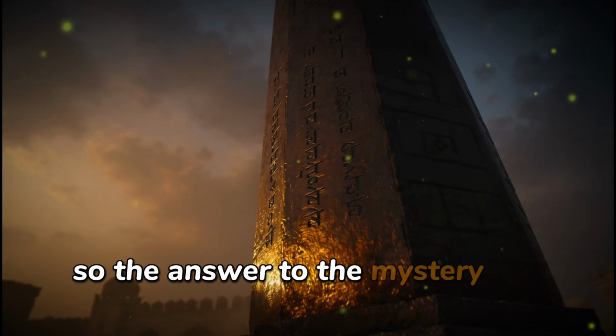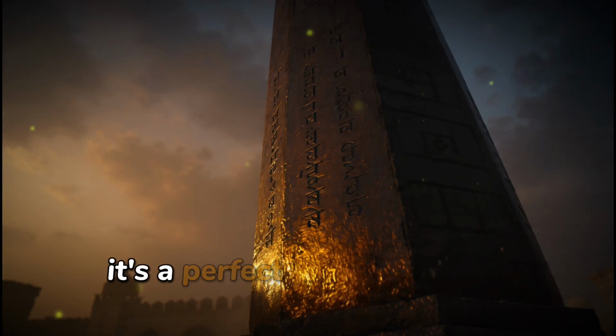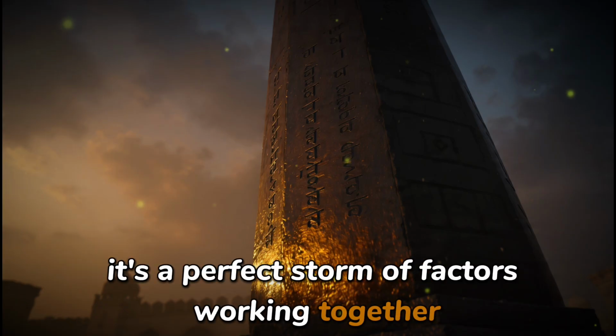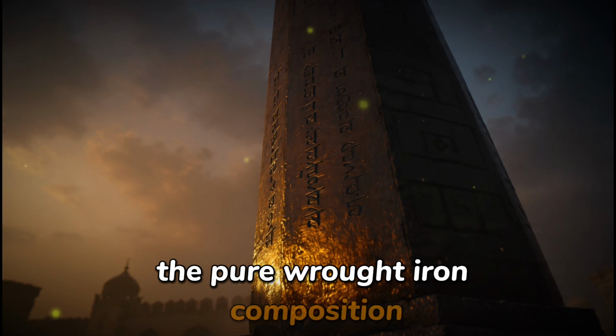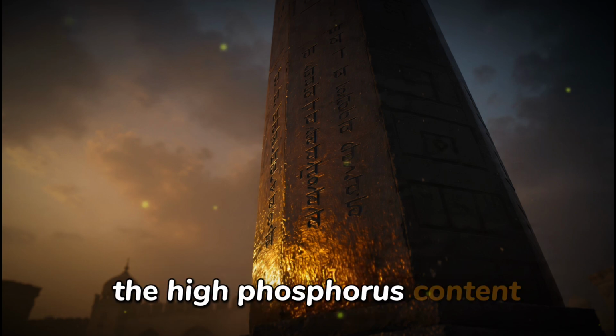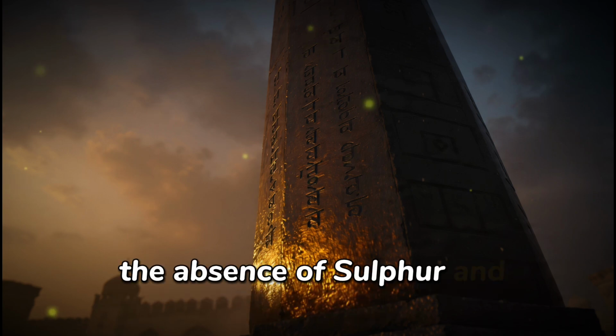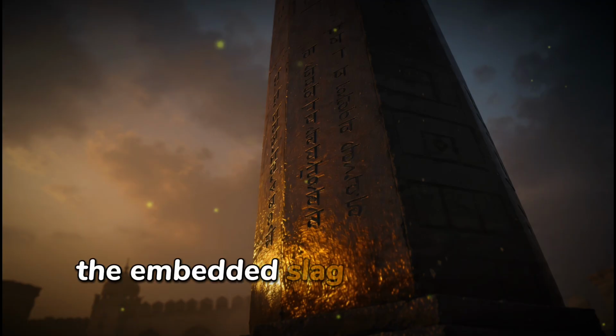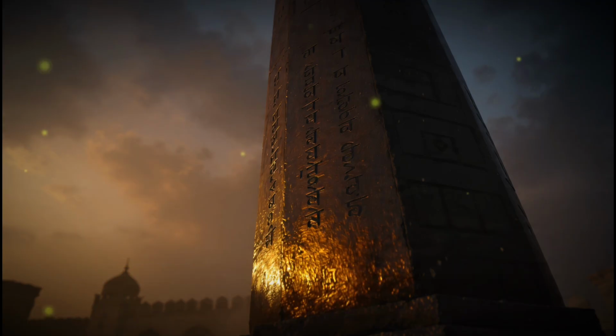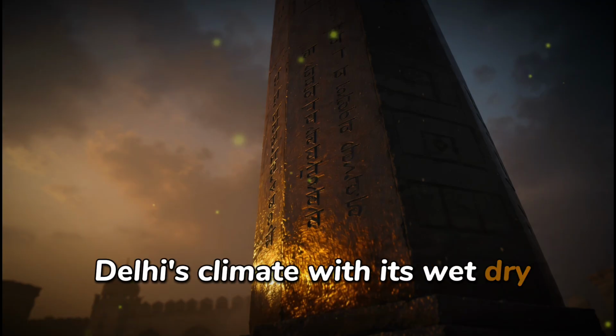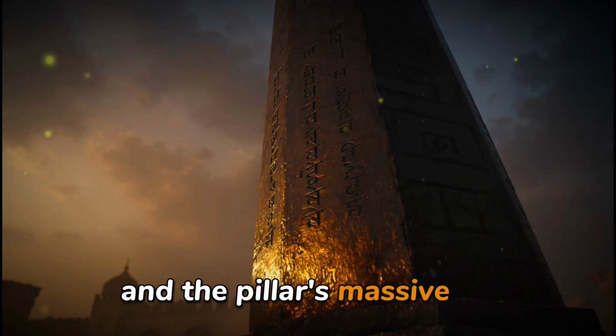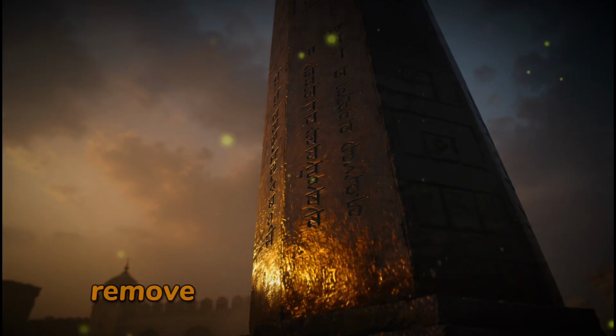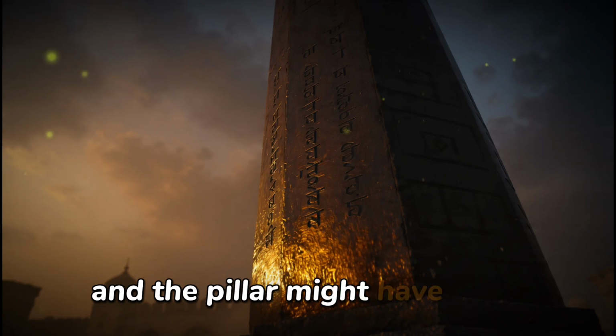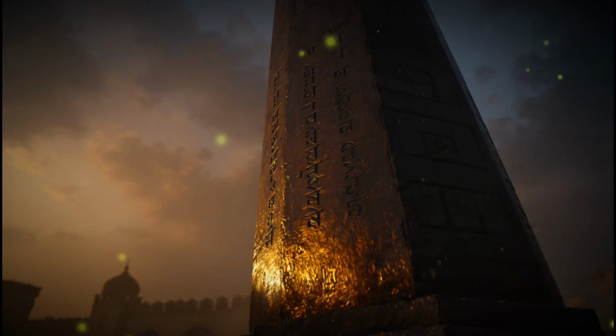So the answer to the mystery isn't one thing. It's a perfect storm of factors working together. The pure wrought iron composition, the high phosphorus content, the absence of sulfur and manganese, the embedded slag particles from forge welding, Delhi's climate with its wet-dry cycling, and the pillar's massive size. Remove any one of these factors and the pillar might have rusted like any other iron structure.